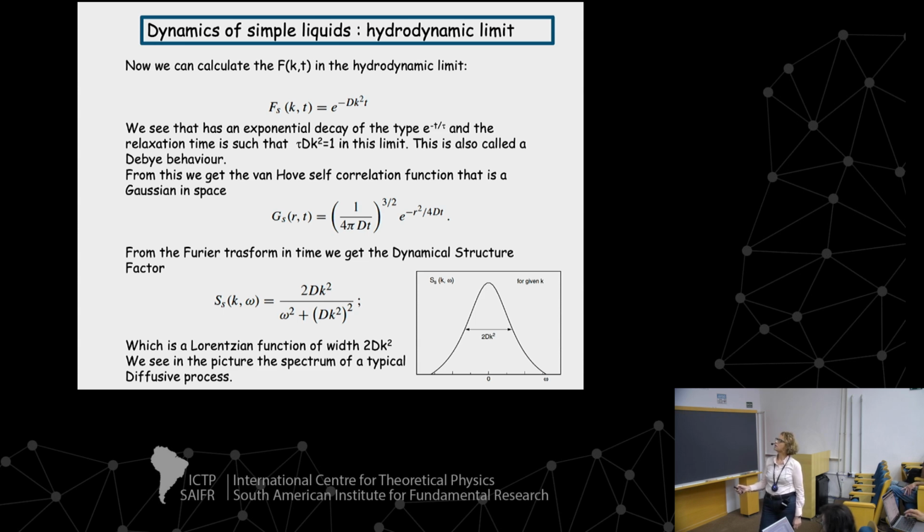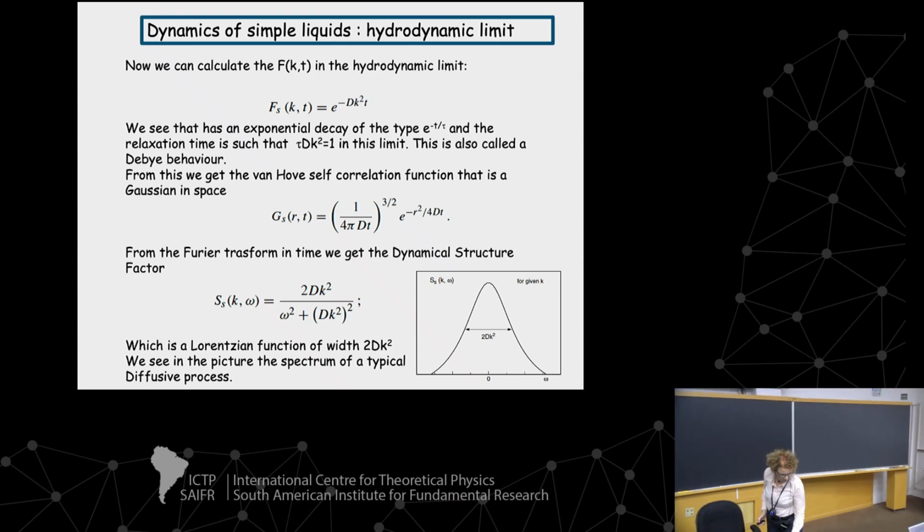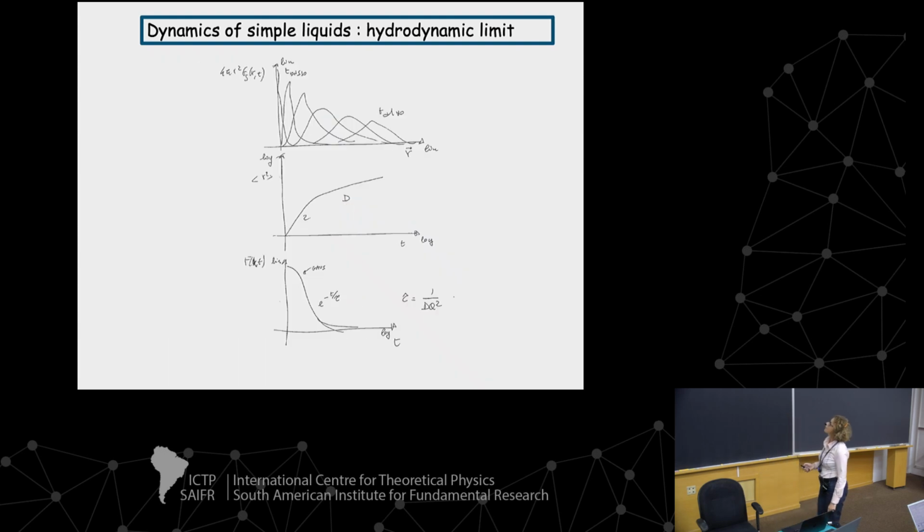This is important always when we want to relate to experiments, because this is a quantity that the experiment measures. In neutron scattering, you measure for water the S_self(k,omega). You remember I told you that hydrogen has this huge incoherent cross-section. So we measure exactly this function. And once you clean your very dirty spectrum of the cell contribution, the multiple scattering, and so on, you are left with this very nice result that you can have directly the diffusion coefficient from the full width at half maximum.